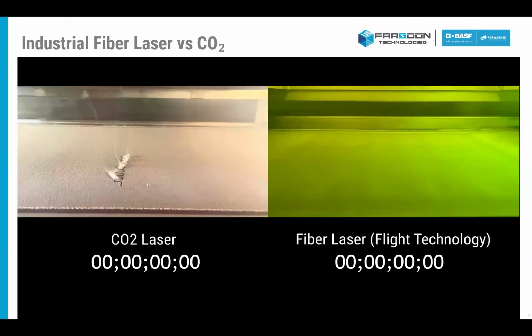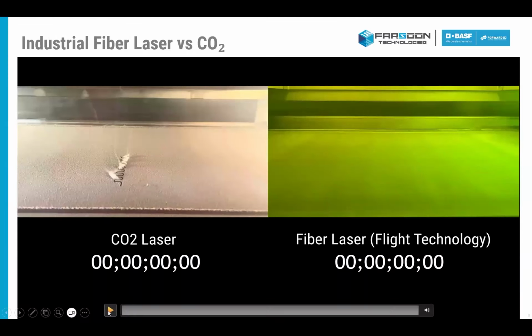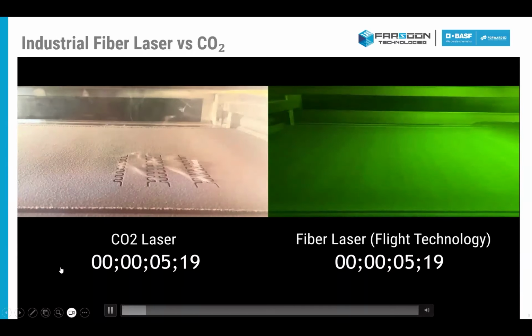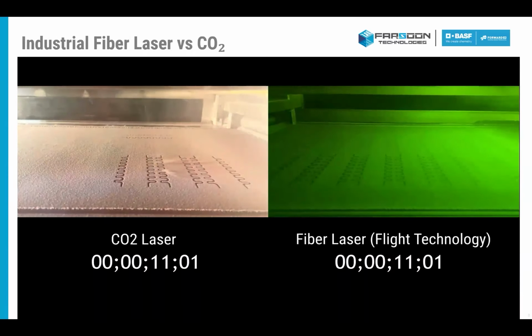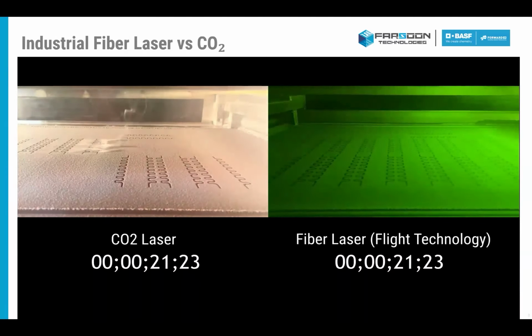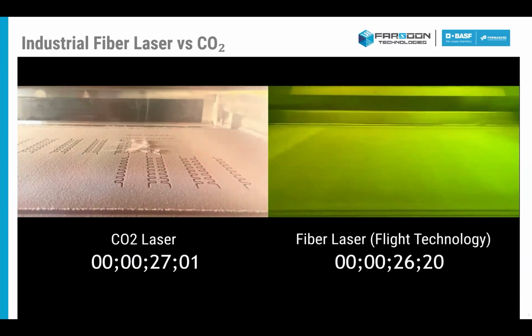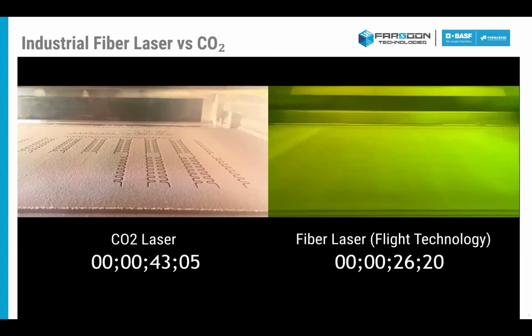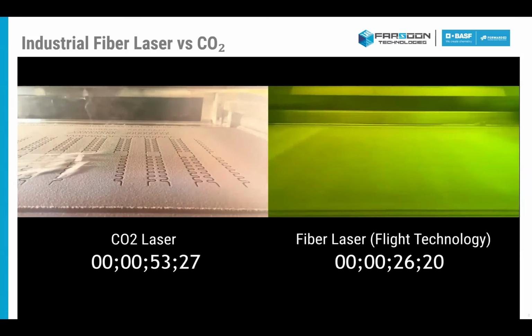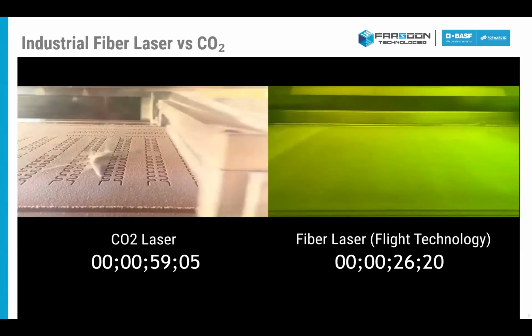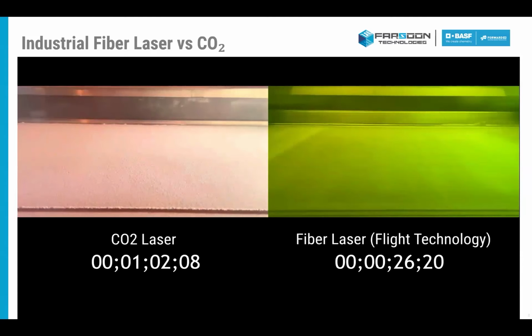So I want to showcase the difference between a CO2 laser and a Flight laser system. On the left-hand side, we can see BASF Forward AM's TPU material being scanned by both the CO2 and the Flight system. The first thing you'll notice is how much smoke there is during the sintering process using the CO2 laser compared to the clean sintering process of the fiber laser. This is due to the way the material absorbs the energy of the laser and leads to increased laser life and reduced machine turnaround time after each build. The second thing you'll notice is the difference in sintering speed between the two.